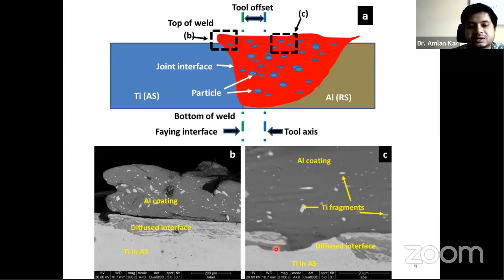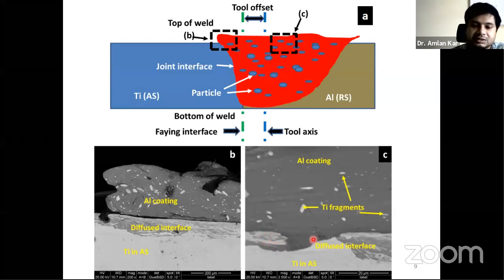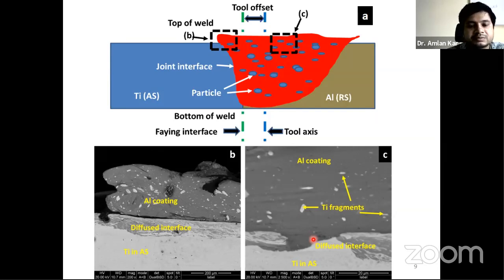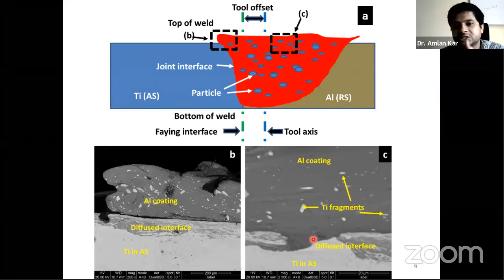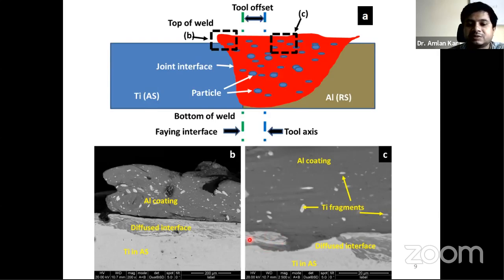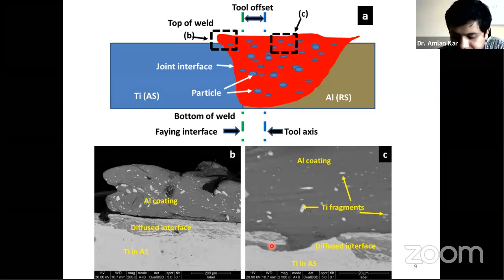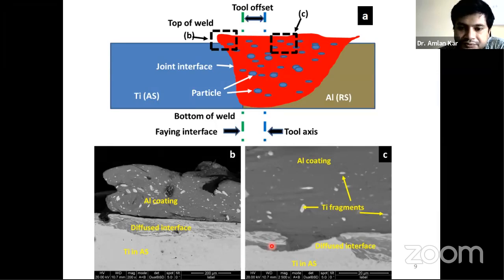What does intercalated mean? Intercalated means you can see there is fragmentation inside the particle, and through the fragments, hydrostatic pressure is developed inside the weld nugget. This hydrostatic pressure pushes the aluminum into the fracture location, and therefore the aluminum and the titanium are clutching to each other. Due to the temperature developed during the welding, there is some diffusion and reaction taking place inside the particle, and this forms a kind of mechanically mixed particle. That is called an intercalated particle. It's a thermomechanically developed particle because temperature and pressure are both involved in developing this sort of particle.